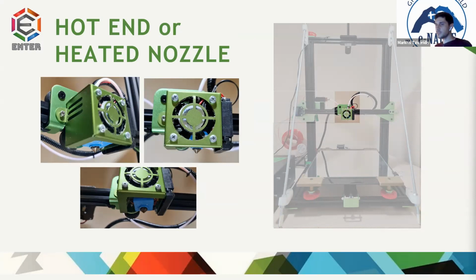The hot end is a critical component of a 3D printer, and issues in the area can have significant effects on the print. The most common issue in a hot end is a clog, which can lead to incorrect extrusion or no extrusion at all. And the common cause of hot end clogs is heat creep, where heat climbs beyond the melt zone of a hot end and material melts too early, blocking the filament path. While certain external factors can prevent heat creep, the quality of the hot end plays a big role. The better the hot end is at containing heat and establishing a consistent melt zone, the less likely we will have a clog.